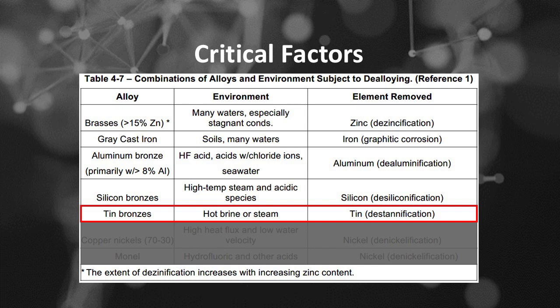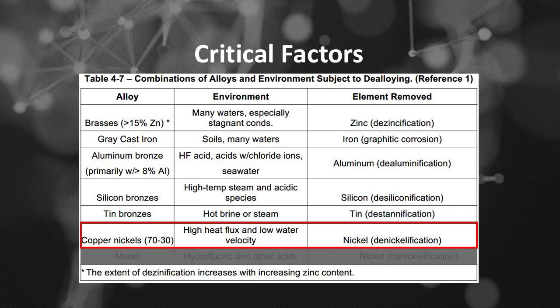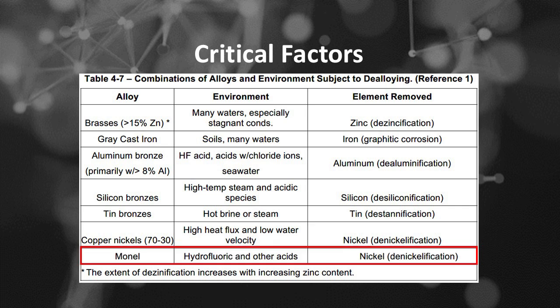If alloy is tin bronzes, and if environment is hot brine or steam, then element removed is tin, or destannification. If alloy is copper nickels, about 70 and 30, and if environment is high heat flux and low water velocity, then element removed is nickel, or denickelification. If alloy is monel, and if environment is hydrofluoric and other acids, then element removed is nickel, or denickelification.